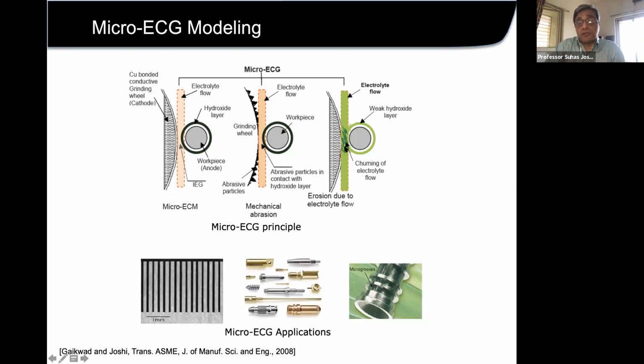We also find that in this process, the gap being very small and the velocities of the flow of electrolyte and surfaces being very large, some kind of turbulence is created, which also generates shearing stresses on the surface, and it helps remove that oxide hydroxide layer formed and expose the new surface.